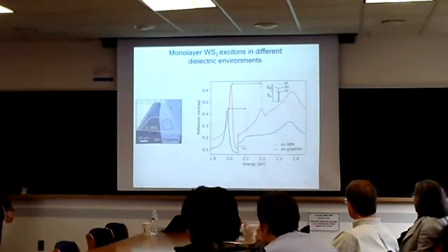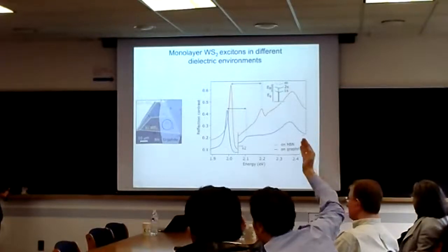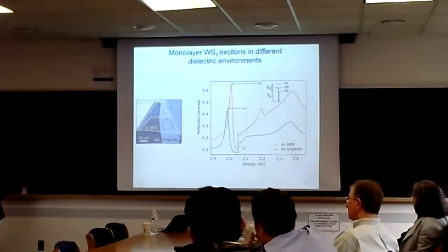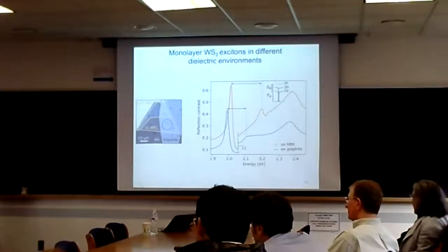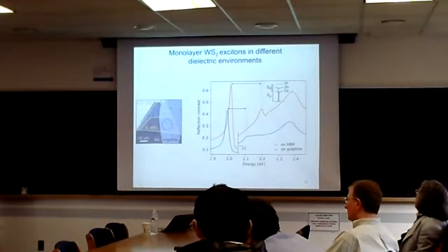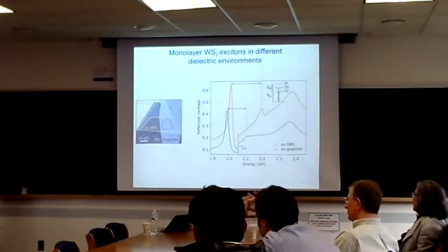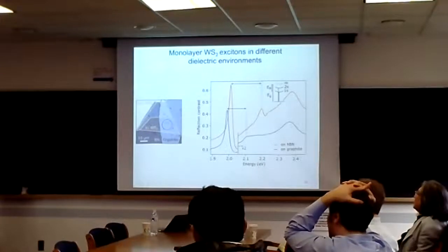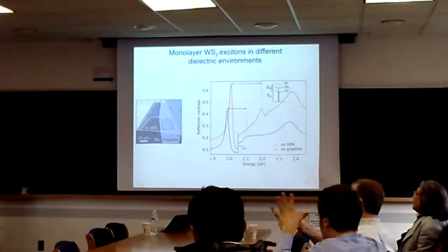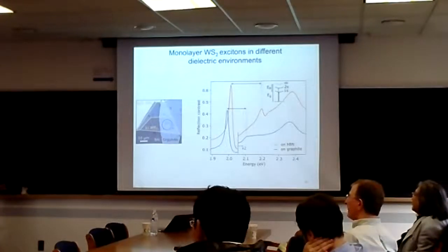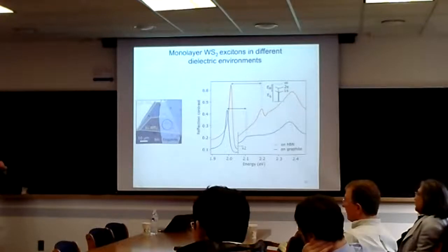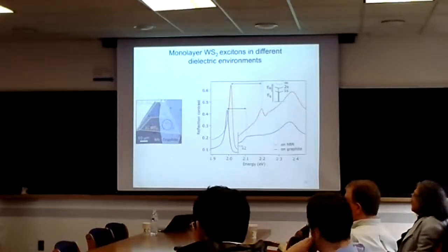Yeah, you can read out a little bit about the doping. So when you say charging, you mean there's some residual doping? No, I mean your sample floats. We never look at a floating sample. Floating meaning the voltage at which the sample sits changes a little bit when you ionize it, and it changes by an amount that depends on the details of the dielectric. That gives you some uncontrolled rigid shifts on a quantity that I don't know how big it is. Right, that's my question. We use the secondary electron emission as the reference for that. If you measure it for hours and hours, that secondary electron emission will shift, and we use that as a reference. That effect happens, and we just have to make sure we are within that.